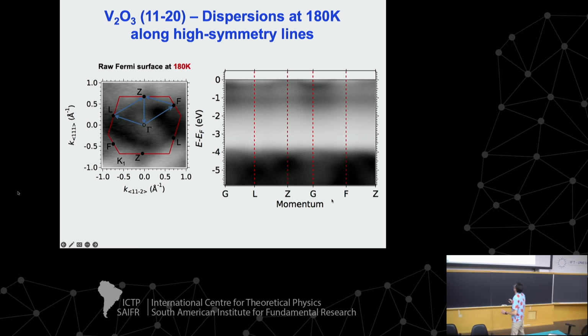So this is an experimental spaghetti band diagram in the metallic state. And this is raw data. This is why I prefer to show the second derivative as a first approach, but I think I am not cheating you. By now you know the data, you can clearly see that around the gamma point there is indeed an electron pocket in the raw data.